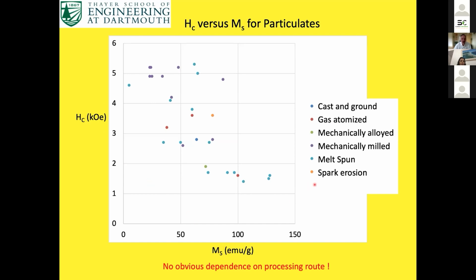coding here is for the different processing methods. And actually what I want to point out from this is if you look at all these different processing methods, none of them seem to be the optimum. For instance, the light blue here is melt spinning, and you can get values all over this graph. You actually want to be up in this right-hand corner here to have the highest coercivity and highest saturation magnetization. But if you look at this, there's no obvious route that's better than any other route.